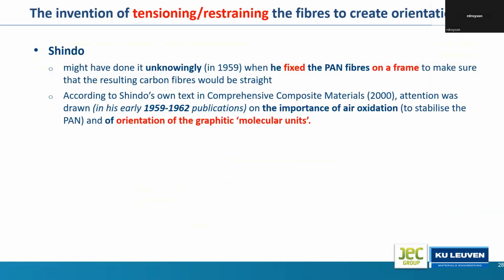So looking very quickly through it, in fact, if you read attentively what Shindo has been doing, he fixes the PAN fibers on a frame to make sure that the fibers stay straight during that oxidation and carbonization treatment. But he mentioned in one of his papers that not only the air oxidation is important, but also the orientation of graphitic molecular units.